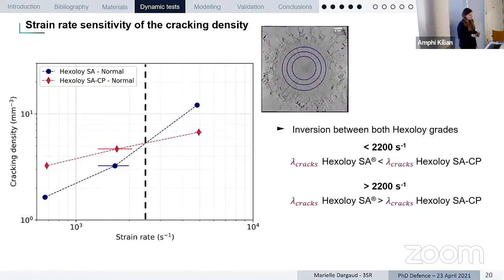First, we can see that for both materials we have a sensitivity, but for the material Hexoloy SA we have a higher sensitivity. What is very interesting is that we have a threshold in between. We have an inversion of the behavior of the intensity of fragmentation for both materials. So the Hexoloy SA material presented a lower fragmentation intensity at low strain rate, but once we go above this threshold, it presents a higher level of cracking.